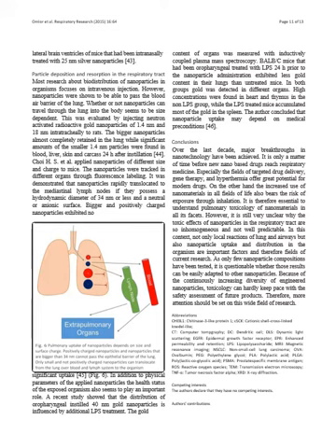Choi H.S. et al. applied nanoparticles of different size and charge to mice. The nanoparticles were tracked in different organs through fluorescence labeling. It was demonstrated that nanoparticles rapidly translocated to the mediastinal lymph nodes if they possess a hydrodynamic diameter of 34 nanometer or less and a neutral or anionic surface. Bigger and positively charged nanoparticles exhibited no significant uptake.